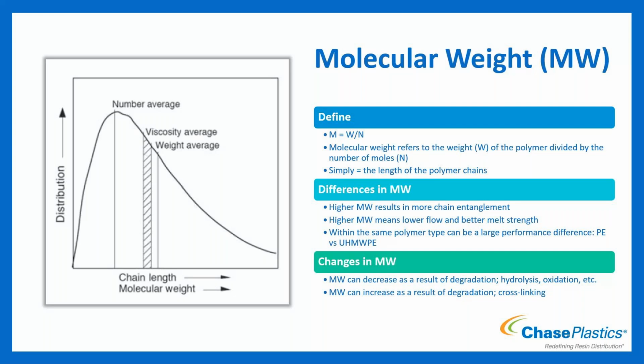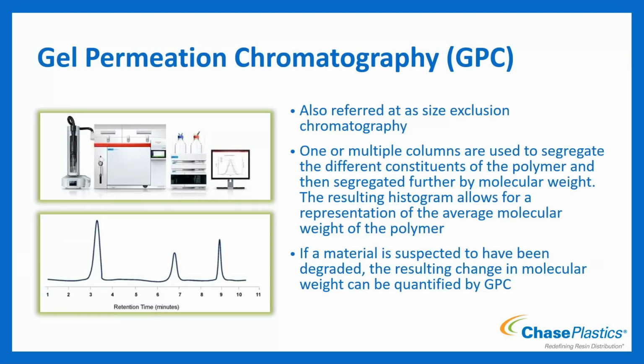So with that, gel permeation chromatography, GPC, is quite a complex process. It's sometimes also referred to as size exclusion chromatography, if you've heard it that way. But essentially it uses different columns, one or multiple, depending on how sophisticated it's getting, to segregate the different constituents of the polymer. So in the case of maybe it's using more lower molecular weight type stuff and it's got additives and stuff, pull it apart from the base polymer. And then we continue to segregate it even further by molecular weight. So being able to do that allows us to get an average molecular weight of the polymer. It's representative of all of it because within the separation of the molecular weight, we can get the distribution as well. And so overall, though, it gives us the average molecular weight of that polymer.